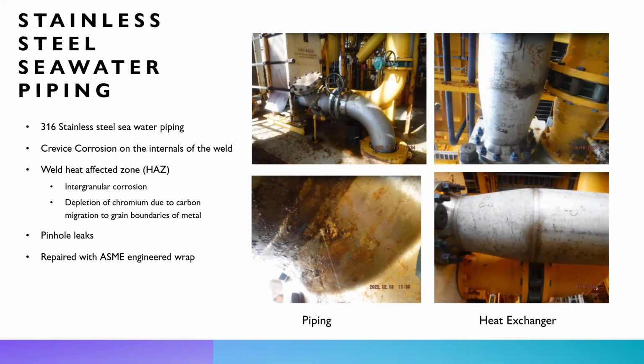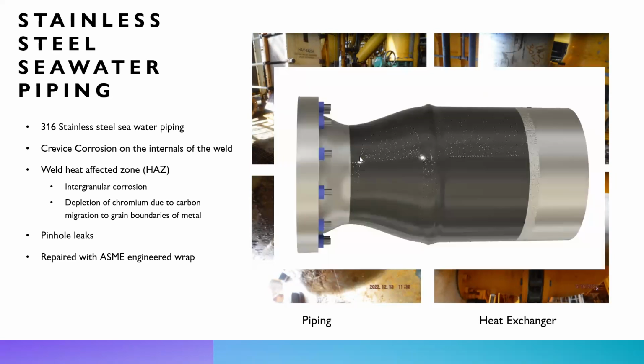It was undetermined. Since they were in service and couldn't really go down and do a detailed inspection, it could have been a little bit of internal corrosion at the weld, which could have been a combination of crevice corrosion or a weld heat affected zone corrosion. But anyhow, it was localized at the weld. It did end up leading to a pinhole defect. They were able to do a small shut-in, and we came in and performed an ASME engineered wrap.